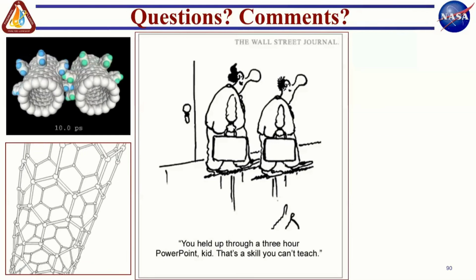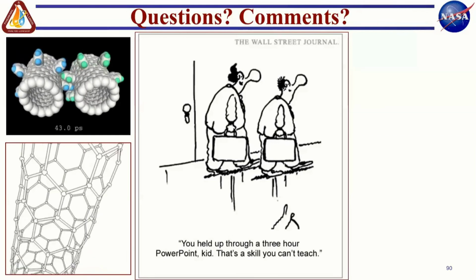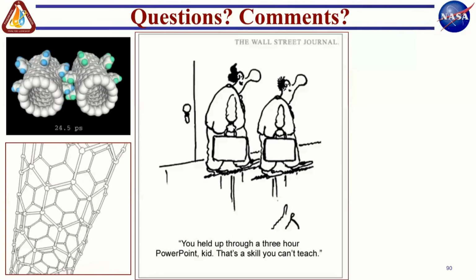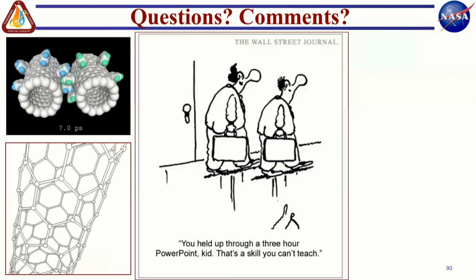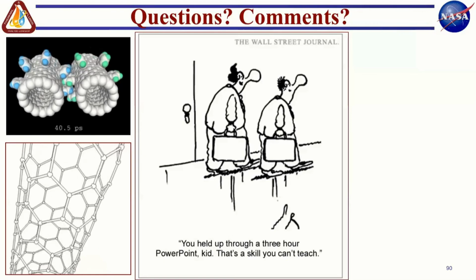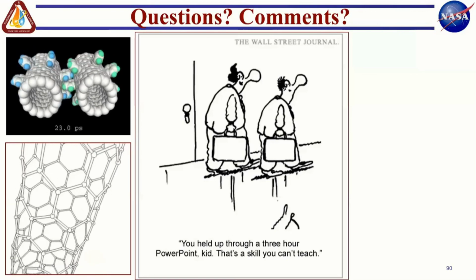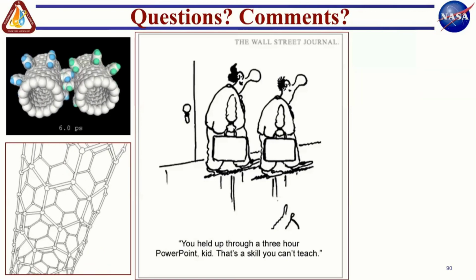But on the other hand, if you surface functionalize the carbon nanotubes, that enables hydrogen bonding, either with amine group or a carboxylic group. You boil the carbon nanotube in a carboxylic acid or an amine functionalized acid, for example.